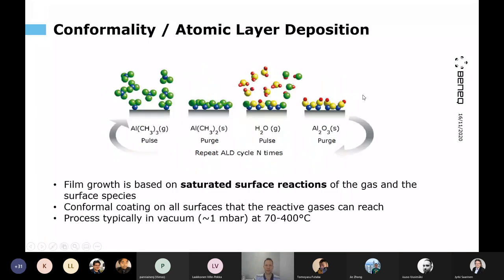Okay, and what is ALD, or what happens during the ALD process, is described next. So basically, we have some part that we want to coat. We put that inside the so-called ALD reactor or ALD tool. And typical process conditions are that it's under vacuum, not always, but usually under vacuum. Typical process pressure is about 1 millibar. And then we heat it up to a suitable process temperature, which is typically somewhere between 70 and 400 degrees C.